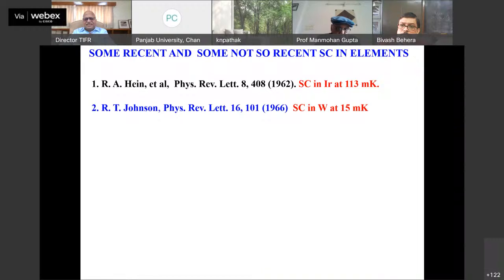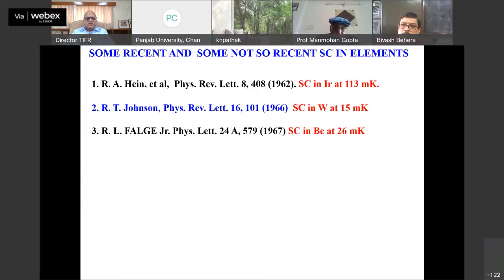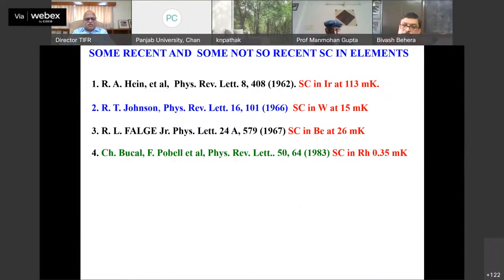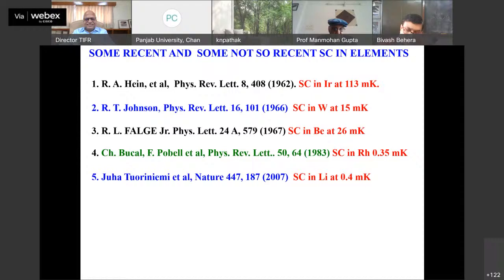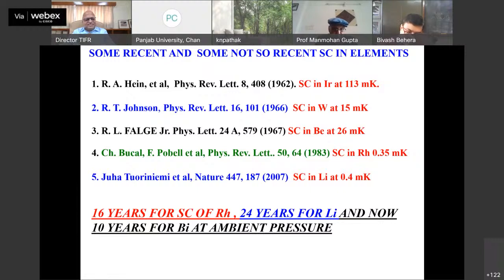Once superconductivity was discovered in mercury, other materials started coming in. Many of them in the periodic table were discovered. The ones at very low temperatures took a little longer, like superconductivity of iridium, tungsten and beryllium, and superconductivity of rhodium. That was done by Pobell more than, let's say, 40 years ago now. And then the superconductivity of lithium happened. So it took 16 years for rhodium superconductivity to appear and 24 years for lithium superconductivity to be demonstrated. And now after 10 years, we have the superconductivity of bismuth at ambient pressure.